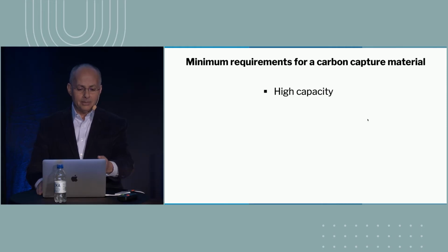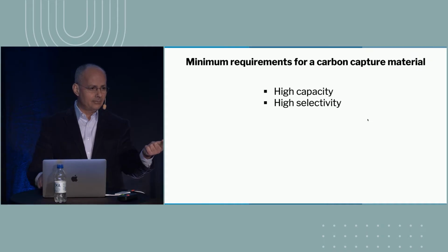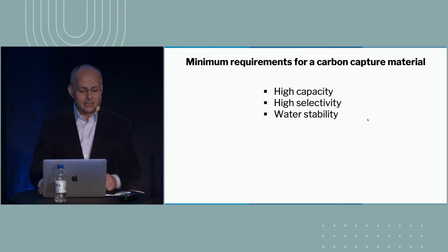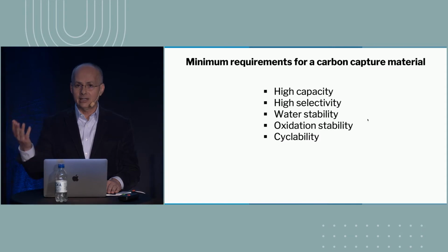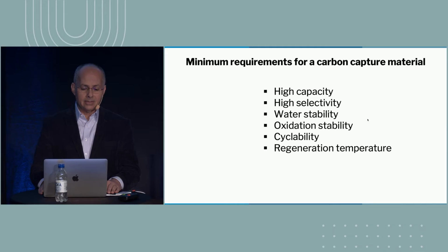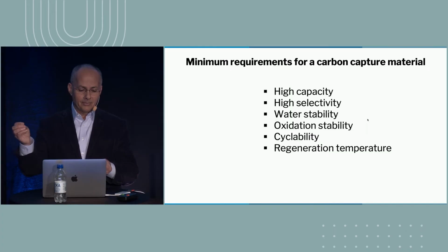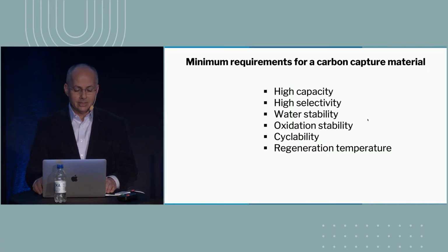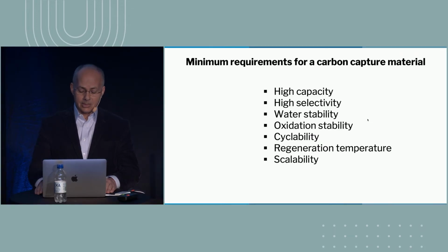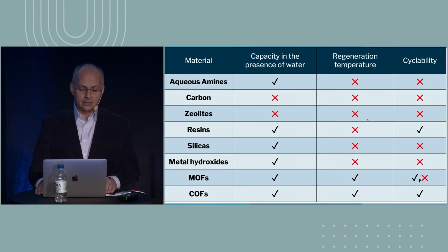So the minimum requirements for a carbon capture material is that you have to have a high capacity. It has to be selective, because you have to pluck out CO2 from the air, from other gases. Your material has to be water stable. It has to be oxidatively stable. It has to be cyclable. Like I said, you have to cycle for years. It has to have low regeneration temperature. Once you bind it, you have to take it out. And you don't want to put in too much energy to remove it. And the solution has to be scalable. You have to make this in multi-ton quantities.